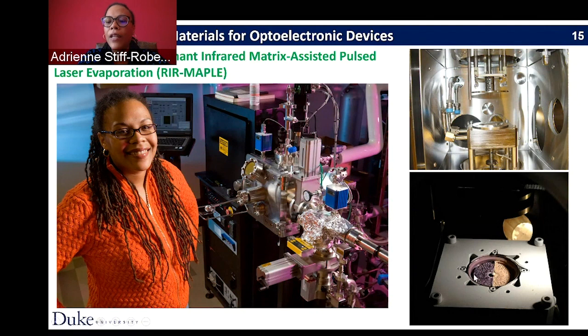Yep. Okay, so as the target cup rotates, the laser's rastering back and forth like this. And per laser pulse, you're getting a scattering of those emulsified particles across the substrate. That's what leads to the nanoscale blending of films. So what that means is that the composition of the target cup gets transferred to the substrate. And so we call this the pie partition. So we've done things where we're varying, from 25, 50, 75% compositions by controlling the composition of the target cup.